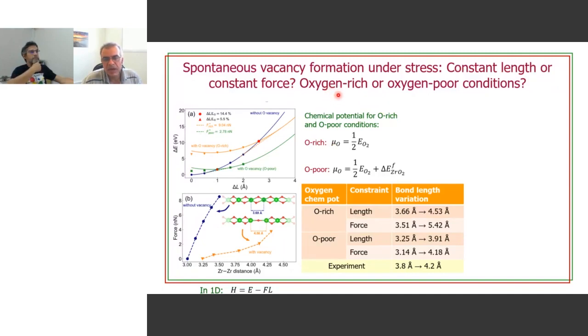in two different oxygen chemical potential conditions, oxygen-rich or oxygen-poor conditions. So the idea is that when you form a vacancy, you have to remove an oxygen atom. And to keep the balance of total energy of this process, you have to take this oxygen atom to a reservoir of oxygens. And this reservoir must be described by a certain chemical potential. And there's a range of possible chemical potentials leading to these two extreme conditions, oxygen-rich and oxygen-poor. This is slightly technical, but if you want, I can come back to this point.